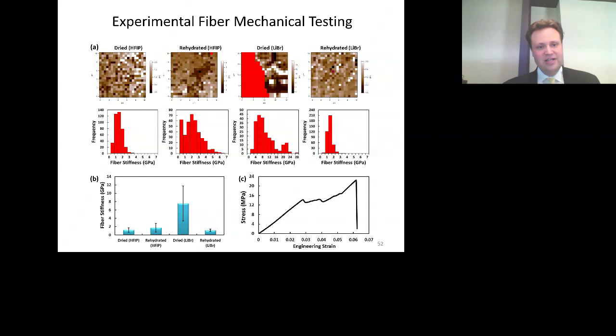We're exploring different solvents, and that's a very important processing parameter, not only shearing, but also the geometric confinement during shearing, but also the different solvent conditions. The way they enter the model is by changing the interactions between the A and the B and the water molecules. These interaction parameters can be derived from an atomistic perspective by running conventional molecular dynamics simulations, which I did not talk about today, but this is how we can get these parameters of interaction for different solvents. And that's how the simulation has driven the experiment.